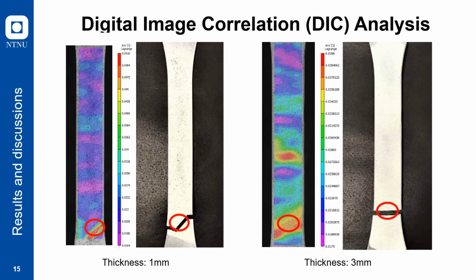Okay, so these are some images of the DIC and the comparison corresponding to the real specimen. You can see from here the highest stress area is showing here, and that's also the area of the fracture. And as you can see from this image, there are multiple areas of high stress, which means the specimen could be breaking from here and somewhere in here as well. So there's also a possibility that the specimen ends up breaking in here.